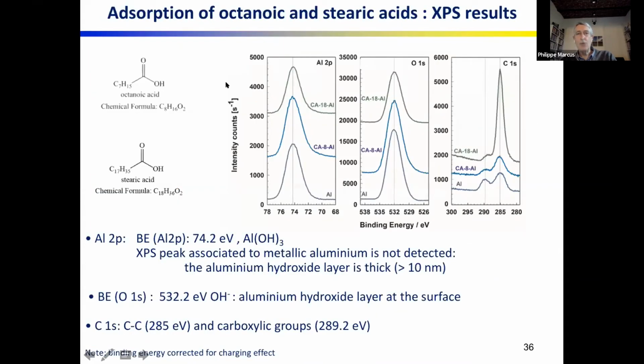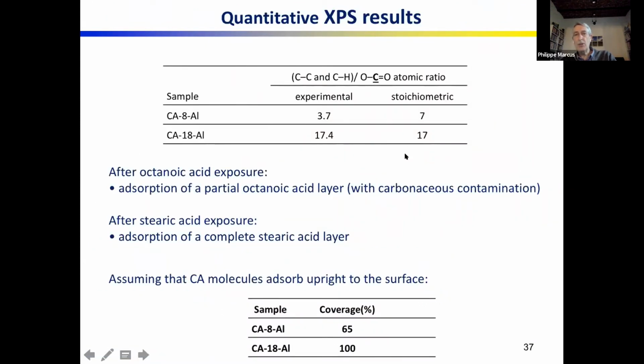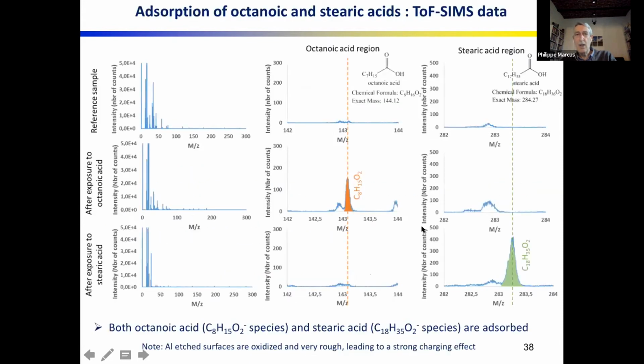So first, we looked at adsorption of octanoic and stearic acids, and the XPS is telling us that both organic inhibitors are adsorbed at the surface. We can state that by looking at the carbon 1s signal. And from the aluminum and the oxygen, we can also derive the chemical states of the aluminum, the amount of oxide and hydroxide. So the conclusion here is that both the octanoic acid and the stearic acid are observed at the surface. However, if we look at the quantitative results, we find out that the coverage is different, and that only stearic acid gives a complete layer of organic molecules. The coverage obtained with octanoic acid is lower than the one obtained with stearic acid. If we look at the time of flight SIMS, so these are mass spectra obtained, the top row is just the aluminum, the reference, the blank experiment.